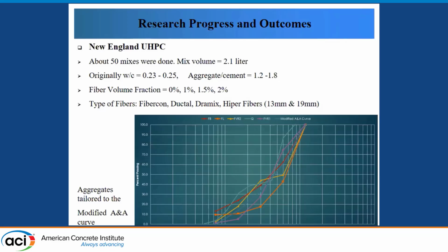In terms of fiber reinforcement, we added fibers in the volume fraction of 0%, 1%, 1.5%, 2%. And we used different kinds of fibers. Some are smooth fibers, some are rough in surfaces. Some have length of 13 millimeter and some are 19 millimeter. But all of the fibers are available in US to comply with the Buy American Act.